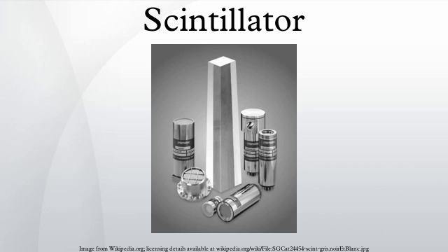is not molecular in nature, as is the case with organic scintillators. An incoming particle can excite an electron from the valence band to either the conduction band or the exciton band. This leaves an associated hole behind, in the valence band. Impurities create electronic levels in the forbidden gap. The excitons are loosely bound electron-hole pairs which wander through the crystal lattice until they are captured as a whole by impurity centers. The latter then rapidly de-excite by emitting scintillation light. The activator impurities are typically chosen so that the emitted light is in the visible range or near UV where photomultipliers are effective.